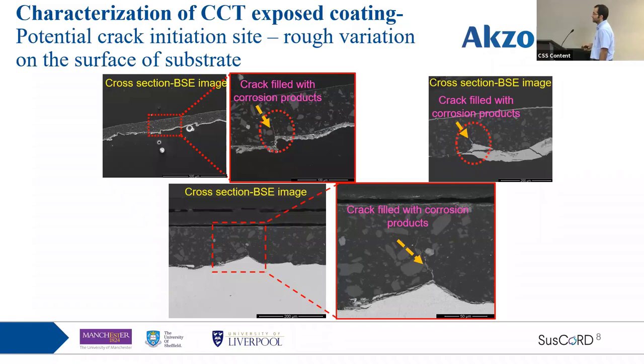But there is another scenario, that this is a stress concentration point within the coating. After a few cycles, it is possible that in this area the coating becomes delaminated from the substrate. And then we know water and oxygen can penetrate into the coating. At this point, corrosion may start at this area, and then corrosion leads to further damage and cracking of the coating.